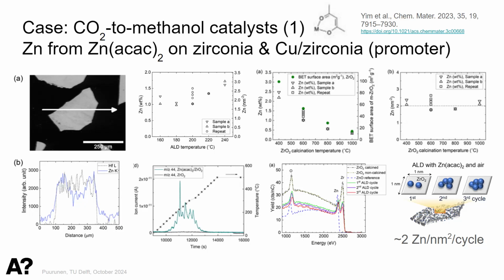Today I was recommending it to some of Ruth's students. So that beautifully shows that we start with this zirconia surface. It shows zirconium and oxygen, and when we add zinc, you directly see it, and the zirconium signal goes down. But what this revealed to us was that we don't have that 2-dimensional growth mode. When we carry out 3 cycles, we don't cover as much of the surface in each cycle. We cover a lot in the first cycle and not much in the other cycles. We are adding zinc, but it's not covering our surface. So from that, we thought that what we are making is these types of clusters, that the zinc that's added likes to have zinc as neighbors, and maybe it's even going on top. I don't know. So can you call it island growth? Perhaps you can.